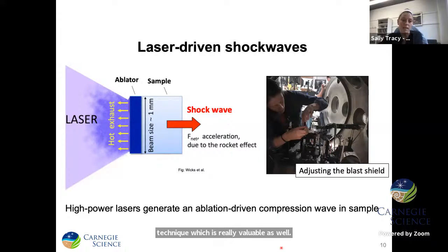So when we use this method, what we do is we use these high-powered lasers to generate an ablation-driven compression wave in our sample. And so here we use a pulse laser, which we focus on the rear of our sample. And typically what we do is we affix what we call an ablation layer to the back side of our sample, which is oftentimes just plastic. And when we focus the laser onto that ablation layer, that forms a plasma, and that plasma expands backwards. And when that happens, that sends a shock wave forwards into our sample through a sort of rocket-like effect.